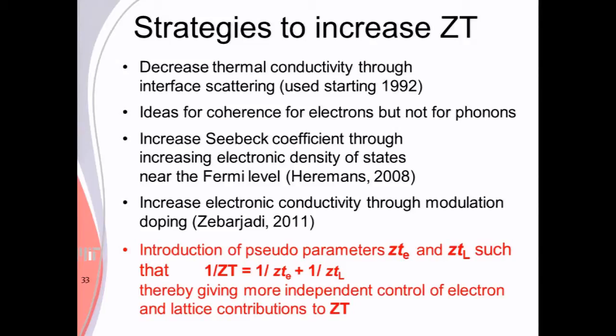So he says, let's break up the ZT into the electronic contribution and the phonon contribution. Maybe we can work with just one of these at a time. We know that if you have more dopants, more defects, more all of this, the lattice contribution is going to decrease. If we have more defects, we'll have more scattering of phonons, so that will make the lattice contribution decrease.